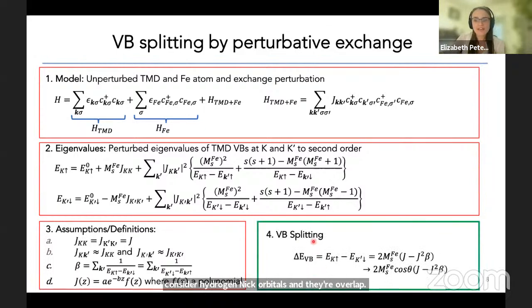And when I put this all together and take the difference between the valence band eigenvalue at K and K prime, and I factor in that you can rotate the magnetic moment of the iron atom, what I get is something that is linear in the Z component of the magnetic moment of the iron atom, but also has this quadratic relationship in the orbital overlap exchange parameter, which captures both this Zeeman-like effect, but also this orbital overlap effect.